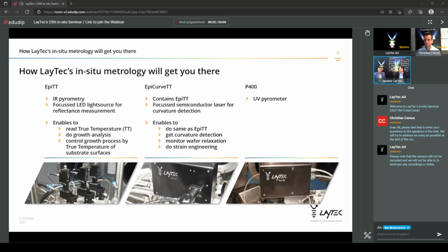Not all layers are suitable for using an IR pyrometer. Therefore, LayTec also has a UV pyrometer in the portfolio. This is the P400 or Pyro 400. This sensor enables you to measure the surface temperature on IR transparent layers, for example, gallium nitride. At UV wavelengths, gallium nitride at growth temperature is opaque, so in that range you are able to measure again the real true surface temperature. And it makes the measurement free from Fabry-Perot oscillations. This is especially necessary on sapphire substrates or PSS, where gallium nitride is grown for LED or laser application.